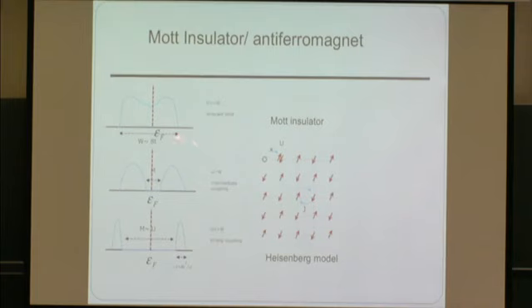To give you a very simple picture of Mott physics, take a single band, and then turn on the on-site Coulomb interaction. So this is a conducting band, and eventually, if U is large enough, comparable to the bandwidth, then you have a split of the band. And if the Fermi energy is in the middle, that's half filling, then you find that this is an insulator, a charge insulator.